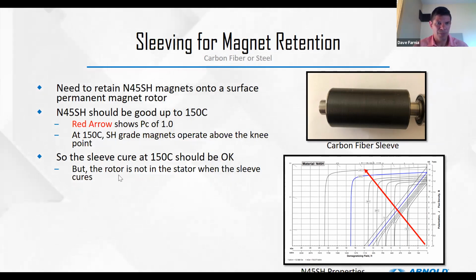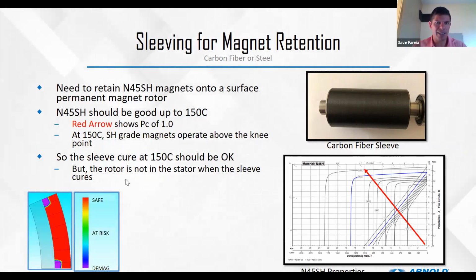But if we sleeve that rotor with carbon fiber, that sleeve has to be cured. Well, we would try to cure the sleeve at as high a temperature as we can, or as close to the operating temperature of the motor as we can. Well, you design the motor to 150 degrees C, so we want to cure our sleeve at 150 degrees C. The problem is that when we're curing that sleeve, the rotor is not in the stator. So we're not in a complete magnetic circuit, which means that with an SH grade magnet, we can get some demag.